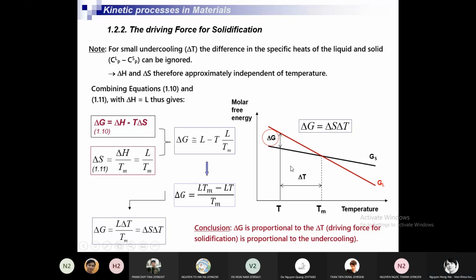It is the temperature range below the equilibrium melting temperature, but the system, the alloy, is still in the liquid state. In this temperature interval, the alloy is still liquid, not solid. And only at the end does the liquid transform to solid. It's the physical meaning of the undercooling. It's a temperature interval below the equilibrium melting temperature in which the alloy is still in the liquid state. Okay. So it is undercooling.